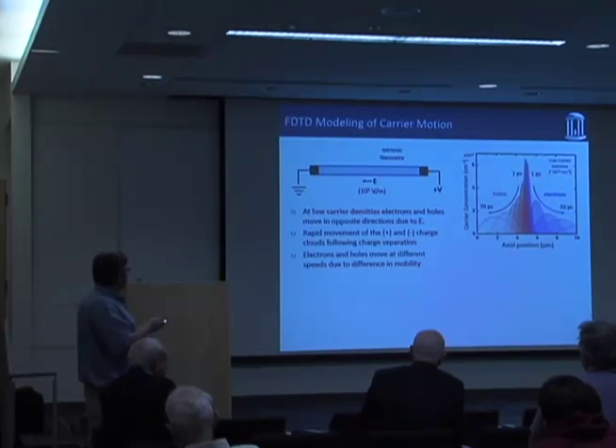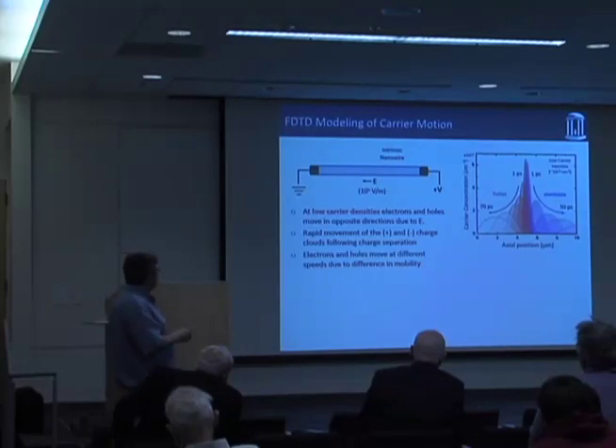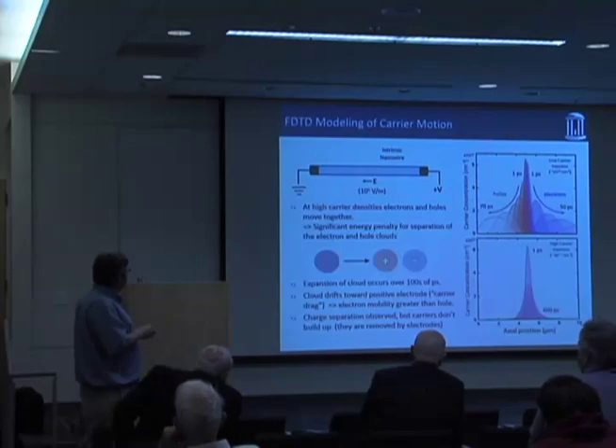And if I have a really low carrier density initially, like say 10 to the 15 per cubic centimeters, you see sort of the electrons move one direction, you see the holes move the other direction. It all looks exactly like you'd expect out of freshman physics, and everything's great. If you increase the density by about 2 orders of magnitude, now all of a sudden you don't see the electrons separate from the holes.